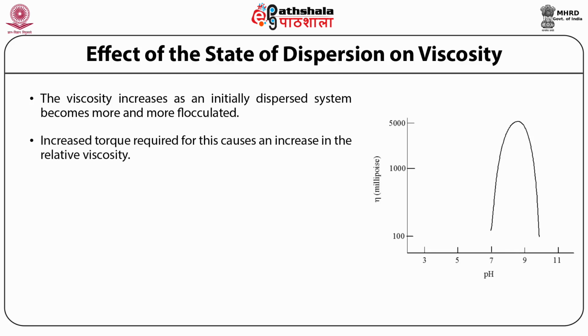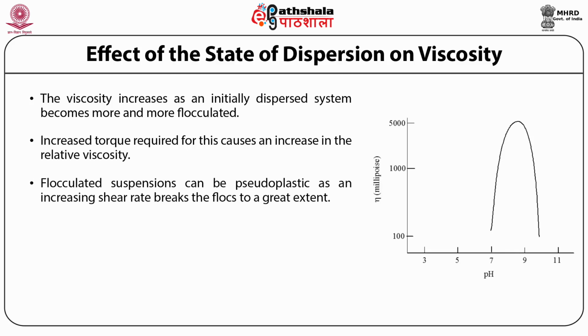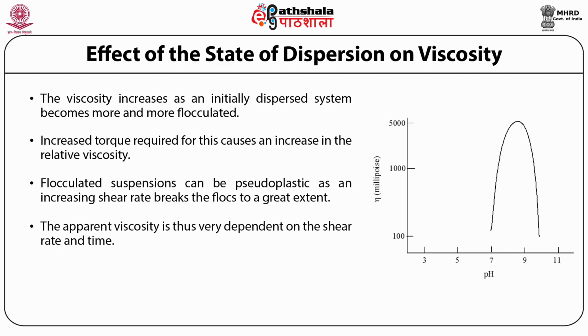The increased torque required for this causes an increase in the relative viscosity. The flocculated suspensions can be pseudoplastic as an increasing shear rate breaks the flocs to a great extent. It can also be thixotropic if more and more flocs break with continued stirring. The apparent viscosity is therefore very much dependent upon the shear rate and time.